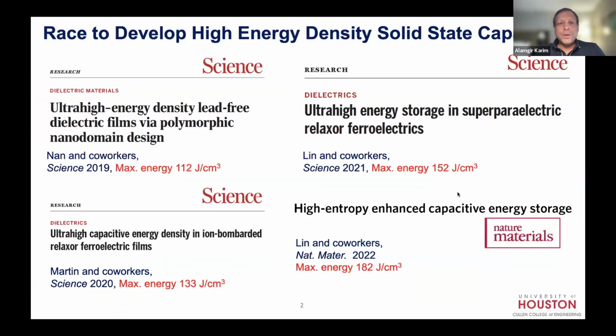If you actually look in the literature, there's a lot of interest, sort of a race, to develop high energy density solid state capacitors. These should be flexible. And you can see what state of the art is getting us, and this is already a few years old. So like 150, 130 joules per cc, that's a lot compared to biaxially oriented polypropylene. BOPP, the industry standard, is more like 2 to 4 maximum joules per cc in packaged form.